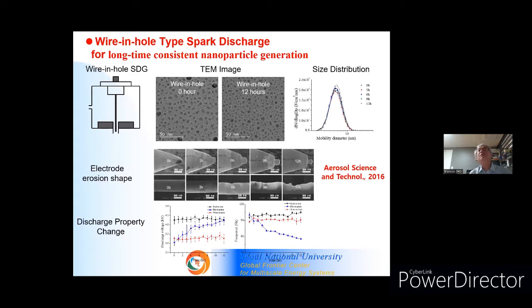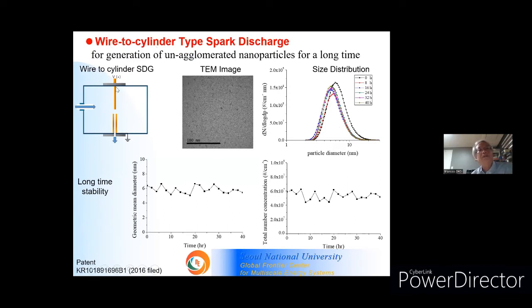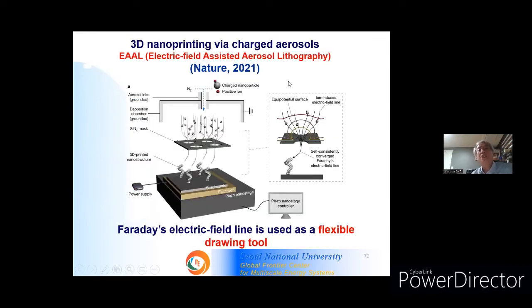Later we found a more practical spark discharge generator: wire to cylinder, a very thin wire and a very thin hollow cylinder. This is very simple, and if we use this wire-to-cylinder type we can generate unagglomerated nanoparticles with very good time stability, long time stability, relatively uniform. So the development of this wire-to-cylinder type spark discharge was very critical for our success in developing three-dimensional nano printing via charged aerosols.